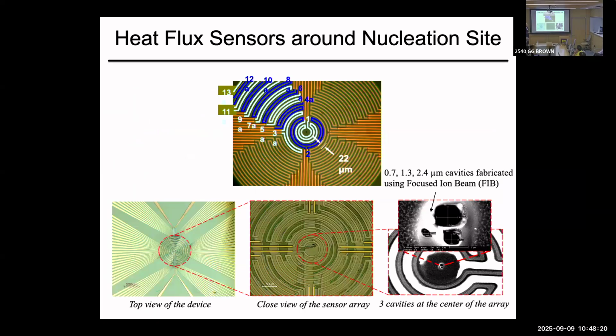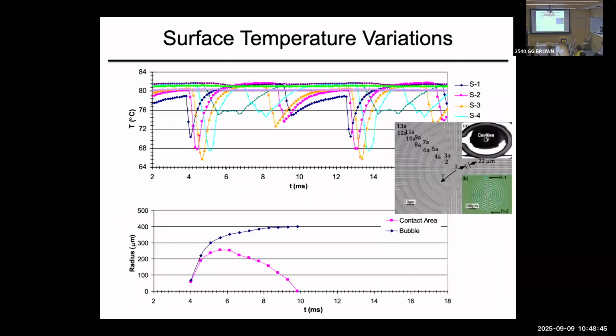In this case, I made basically a sensor array. This is two layers: a heat flux sensor with the top measured temperature, and below that there's another temperature that I measured, the substrate temperature. And these are around cavities. I made different cavities so I can get nucleation at the right time. And then the bubble grows, and I measure exactly the heat flux at any step of the way through the process. So let's look at one event that I've recorded.